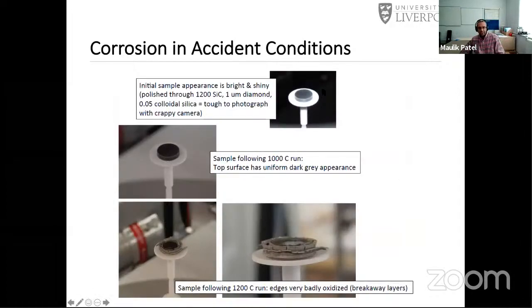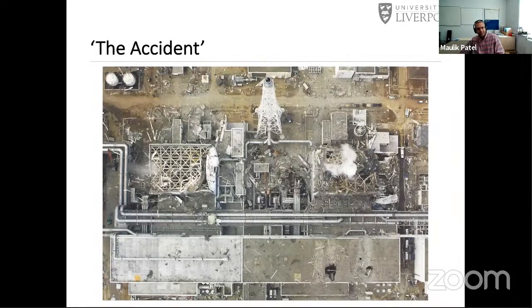This is an example of what happens. This is a zirconium alloy pellet at room temperature. If you heat it to 1200 degrees Celsius, it basically becomes cigarette ash. So your metal goes to oxide. Metal is more ductile, ceramics more brittle. But another thing happens, and you have Fukushima type accidents, because now all your zirconium has absorbed oxygen from water. What's remaining is hydrogen, and you can have accidents that we never desire to have.